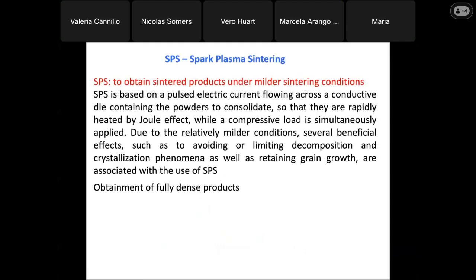Then we also used spark plasma sintering. Spark plasma sintering is a technique based on a pulsed electric current which flows across a conductive die. The die contains the powder which should be consolidated. So such powders are rapidly heated by Joule effect, and at the same time a compressive load is applied. And so due to the milder conditions, several beneficial effects can be obtained, such as to avoid or limit decomposition and crystallization phenomena. And with this technique, you can obtain fully dense products.